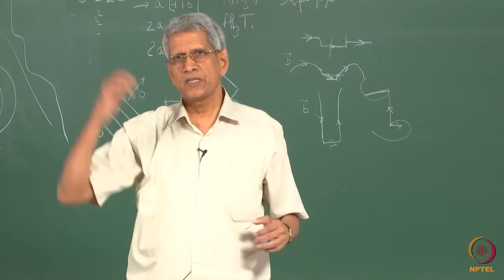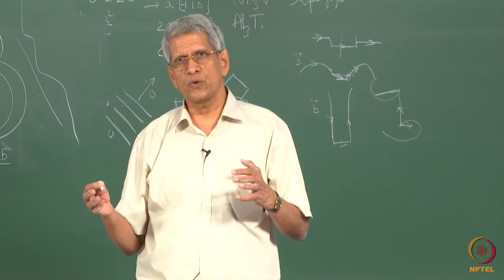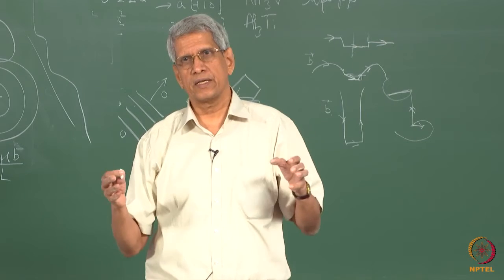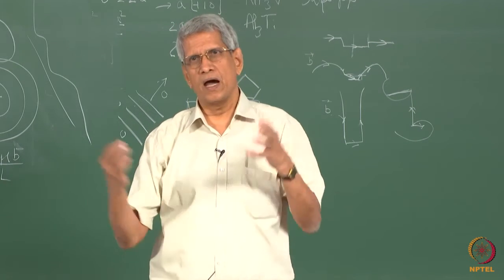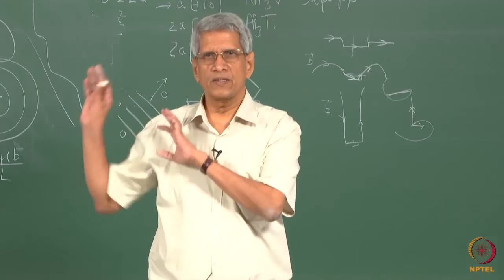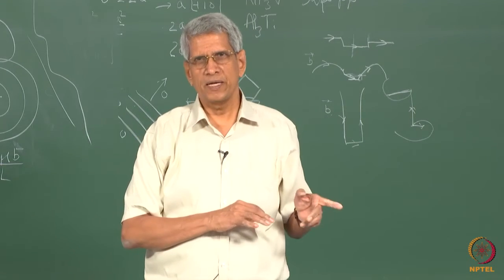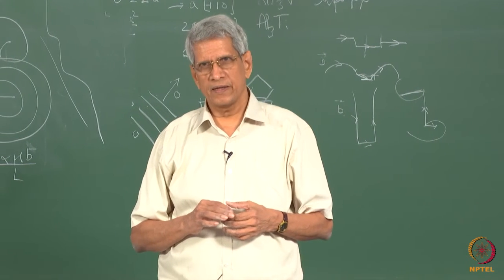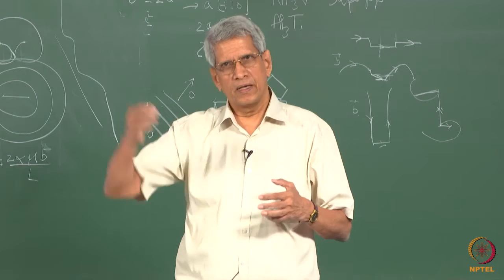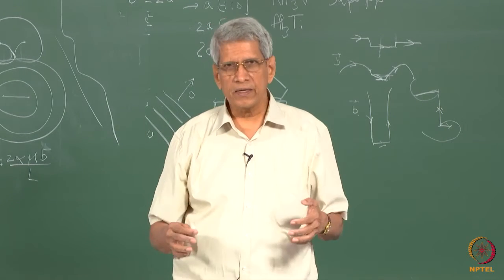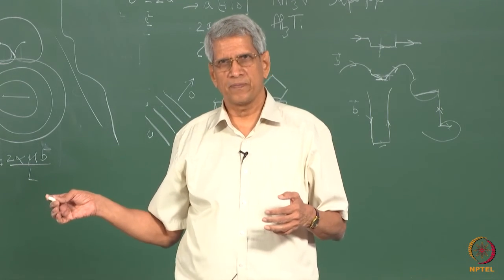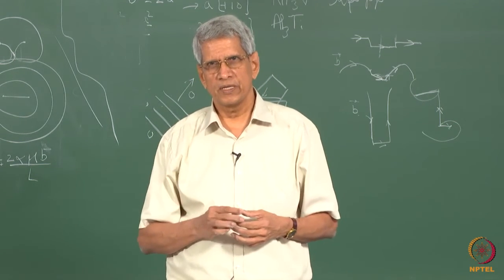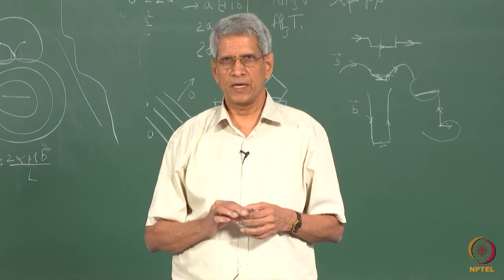This is how, when we deform a sample, quite often one can notice that it all depends upon the stress required to generate a crack within the sample or at the boundary. We are considering a case of a boundary where two possibilities are there. One, it can generate a dislocation on the other side, in the other grain, and relieve the stress, or a crack could be generated. Then also material failure will start. This is one of the ways in which a failure could be initiated from the grain boundaries.